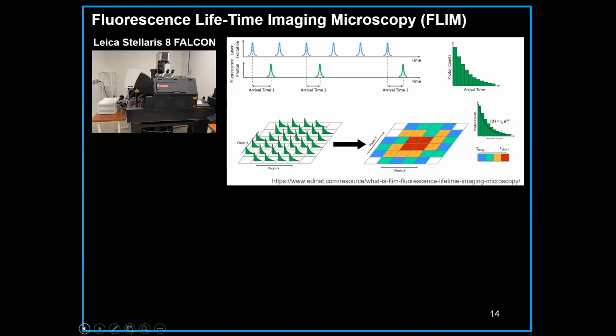And the last capability of this Leica Stellaris 8 microscope is fluorescence lifetime imaging microscopy, called FLIM. In this technique, we also use pulsed laser, and we measure the time between the laser pulse and when the fluorescence photon is detected. It's called arrival time. This photon arrival time is recorded over time, and it creates a histogram of photon arrival times. It scans across the sample, and each pixel will show those photon arrival time histograms. Based on that, the system creates a color-coded fluorescence lifetime image.